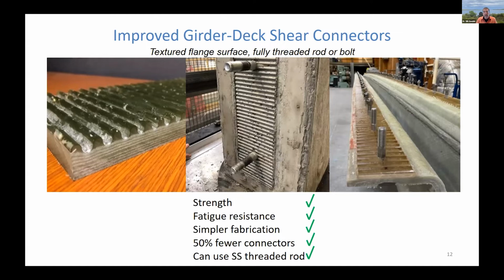textured flange surface. The upper surface of the top flange of the girders, as shown in the picture here on the left, actually has sinusoidal ridges that are formed in there during the infusion process. So as that girder is infused, we have a caul plate that sits on top, and it's not bonded to the girder, but that caul plate has matching ridges, and we infuse resin up in there, and we create these sinusoidal ridges. And then when we cast it against the concrete, as you can see from our shear block specimen in the middle, we get matching ridges on the concrete deck. So now we're transferring shear by mechanical interlock between the concrete deck and the top girder flange.